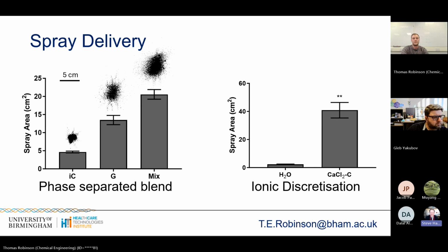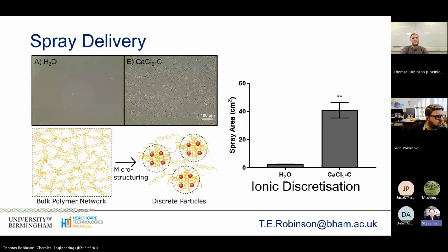If you put it in hot, it doesn't work, and that's because you need that calcium to sit in between the different fibrils rather than inside the fibrils, which is what you get if you put it in hot and then cool it. I do have data to that effect, but I apparently haven't put it in this presentation, so I apologise. But you kind of see that here.